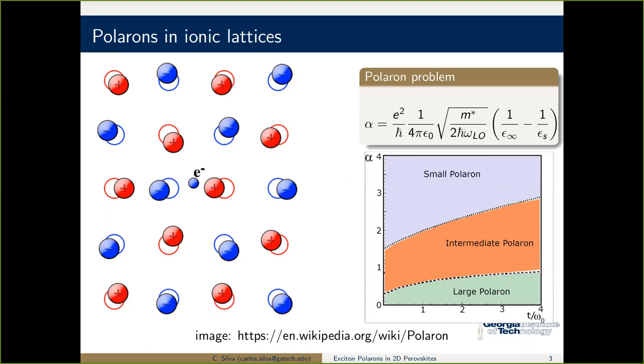And in the perovskites, this is in a slide that I'm about to get to, but it's about 40 millielectron volts for these 2D perovskites. For bulk perovskites, it's about the same, not that different. This comes from a simple model, of course, but it is treated as a phenomenological parameter that we're going to plug into other developments, or just use as a way to do zoology, like in this diagram.